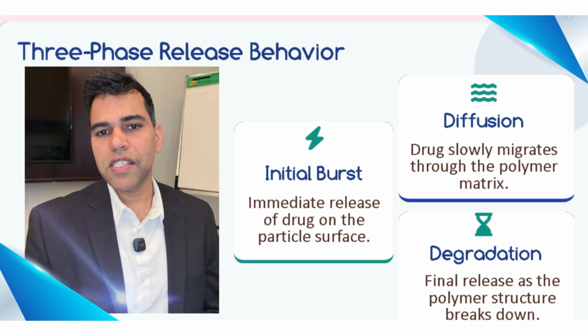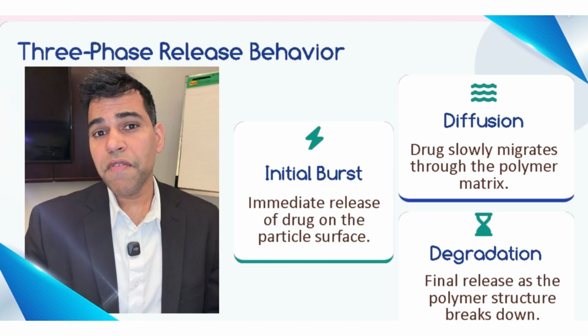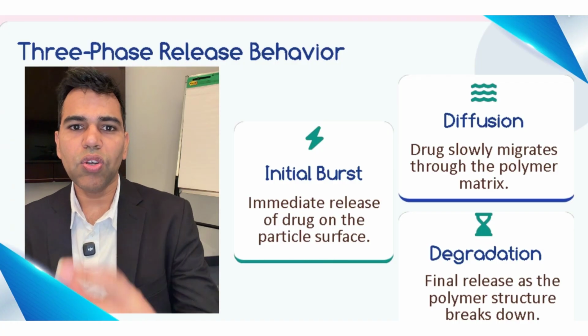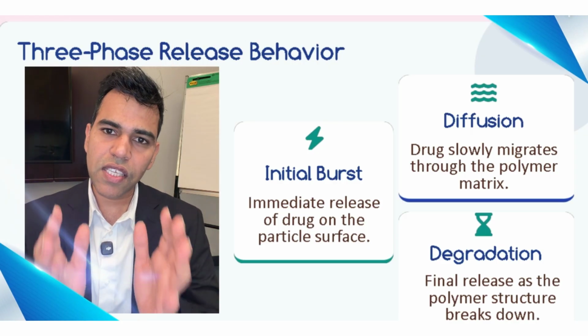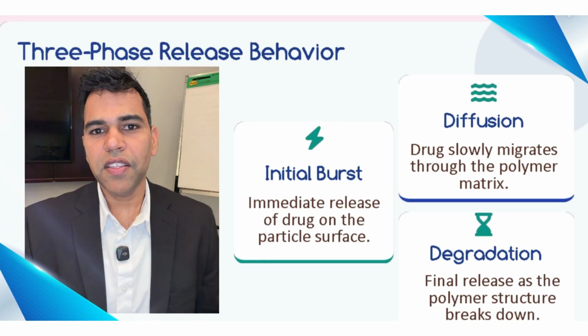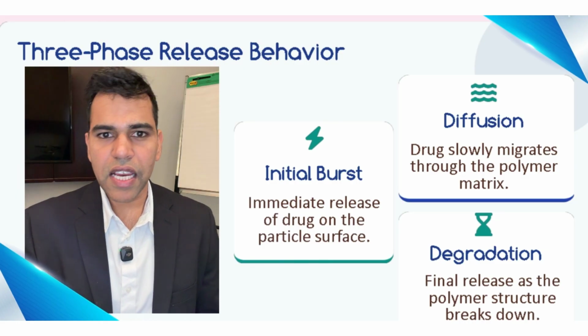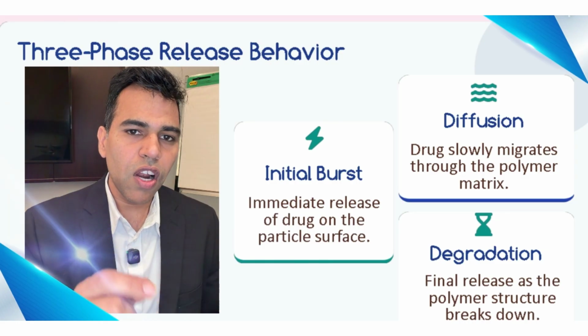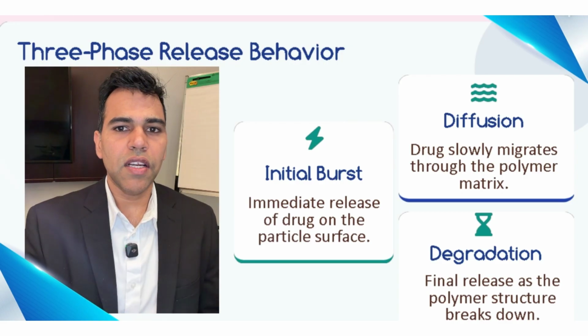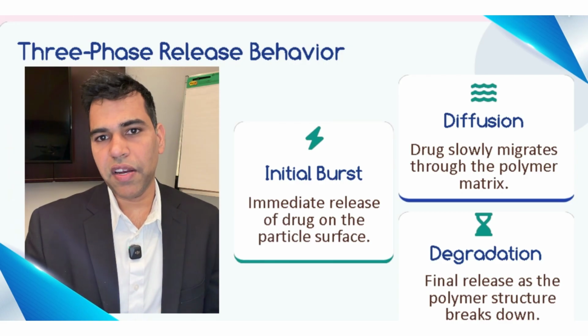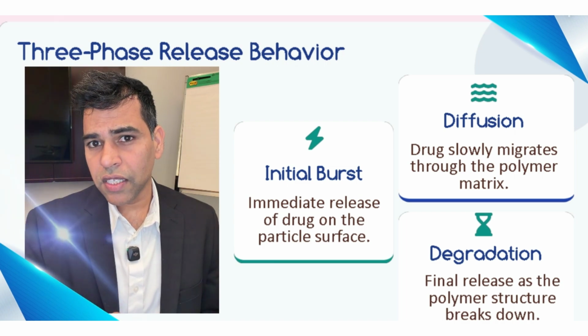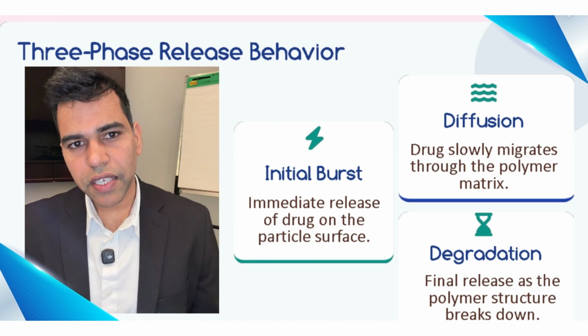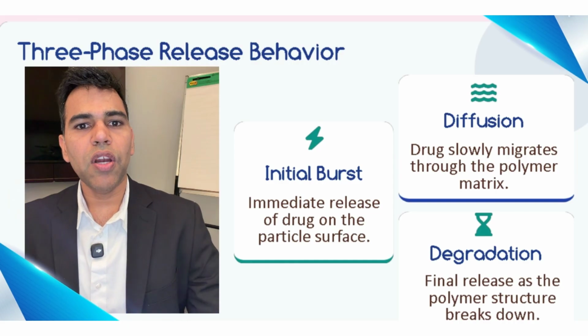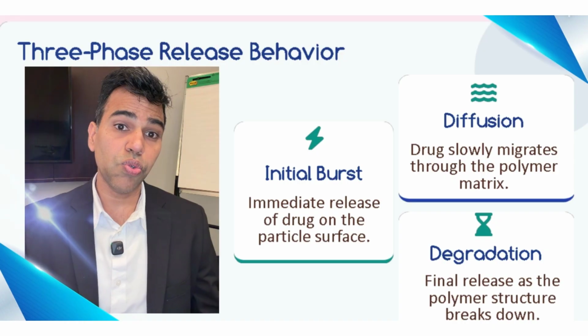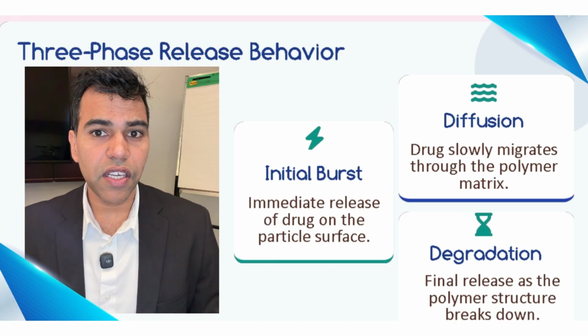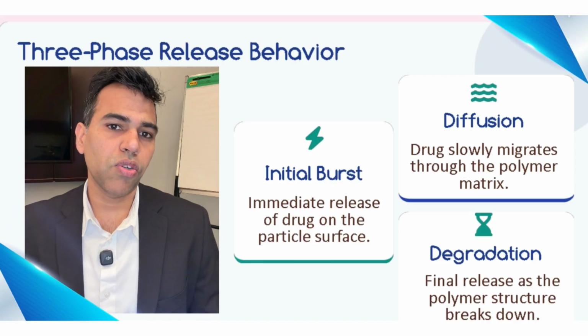You can run in vitro release testing, yes, but the release behavior of a PLGA microsphere in a dissolution bath is not the same as in human muscle. The correlation between in vitro results and in vivo pharmacokinetics, what we call IVIVC, is notoriously difficult to establish for long-acting parenterals. And if your bioequivalence study requires in vivo data with monthly or 3-monthly endpoints, you are looking at clinical studies that run 6 to 12 months per formulation iteration at enormous cost.